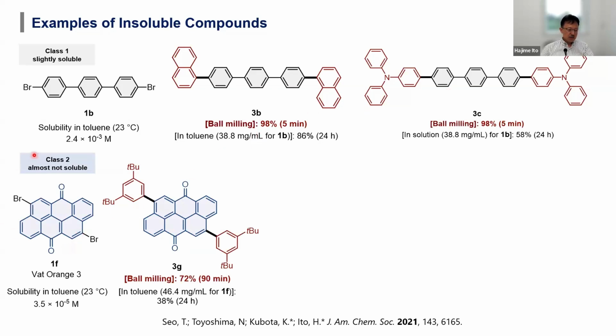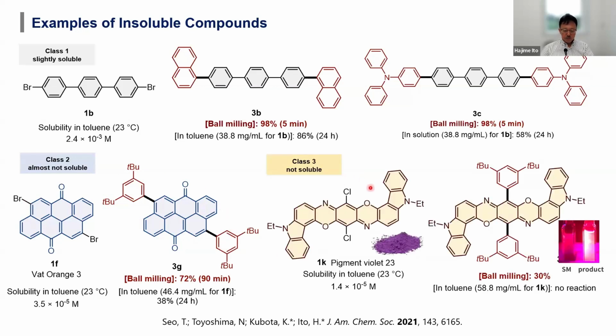This compound is less soluble compared to carbon 60, 10 times less soluble, but cross coupling works very nicely. And this compound is even less soluble compared to carbon 60. This is a pigment, and almost no...